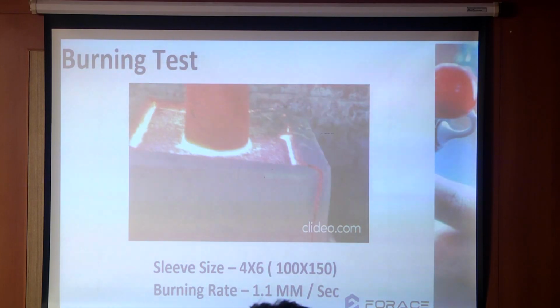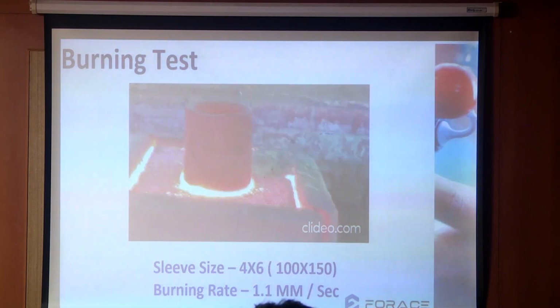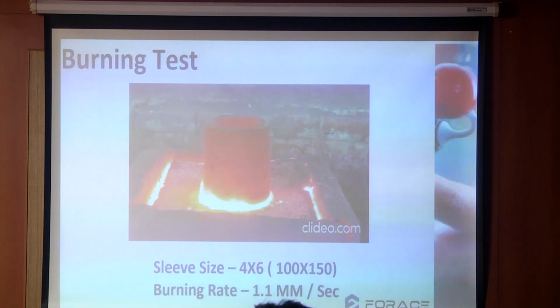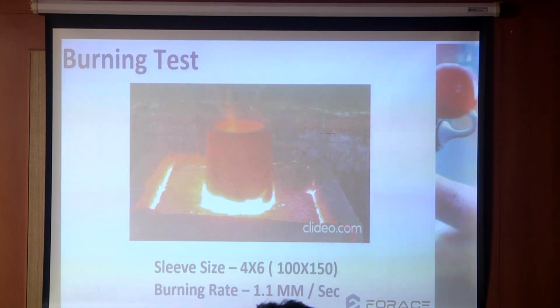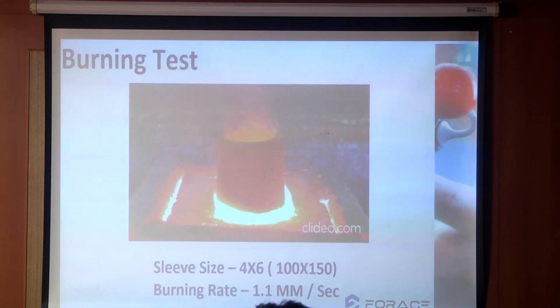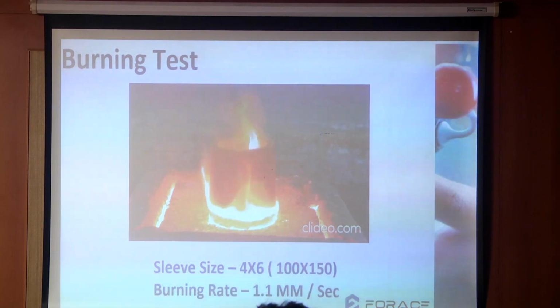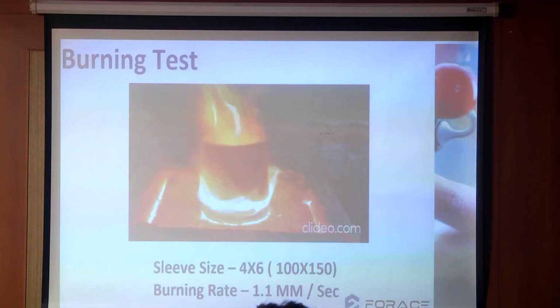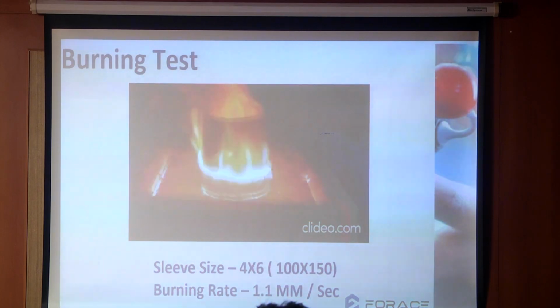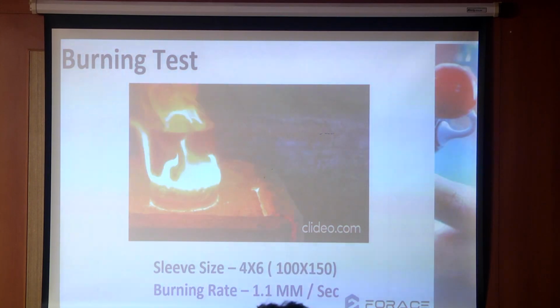This is the burn test or burning rate. We are claiming a burning rate of around 0.9 to 1.1 mm per second. This test we have done in front of the customer, or on the shop floor of the customer where you want to test the sleeve.